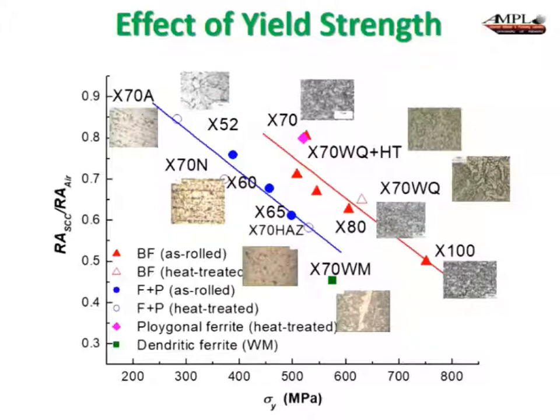And you see, when you relate these curves to the microstructures of the steels, what this did is essentially lead to the elimination of pearlite from the steel completely, and the replacement of pearlite with various additions of things like niobium to form niobium carbide precipitates. And to what degree, though, does the niobium carbide contribute to this trade-off between the two?